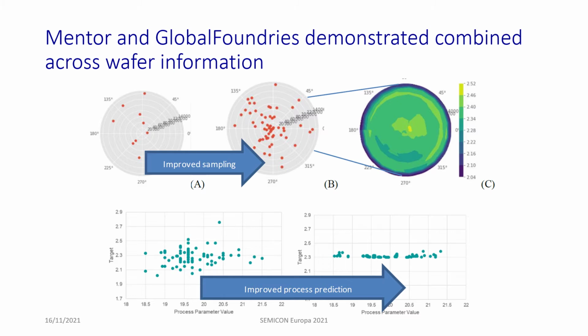Another example of a project result was produced by Mentor and Global Foundries. They have combined data measured on a wafer, and by combining this data, it was shown that you can get a better prediction of your process parameters. Shown in the bottom of this slide is on the left-hand side the situation before this data was combined, showing quite a significant spread in process parameters. And once you combine this information, the spread is very much reduced, leading to a much better prediction of the process.